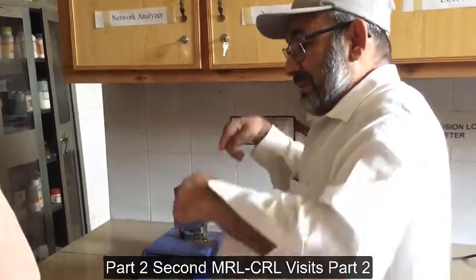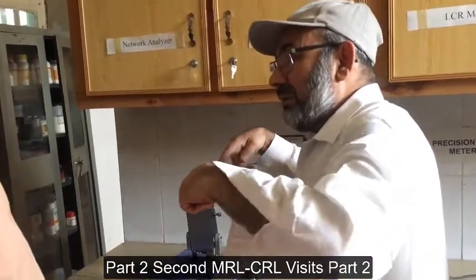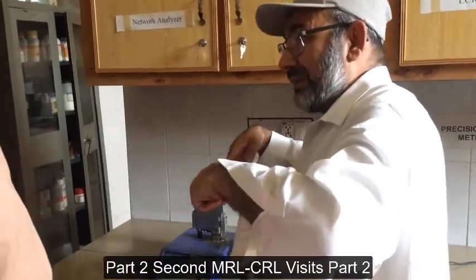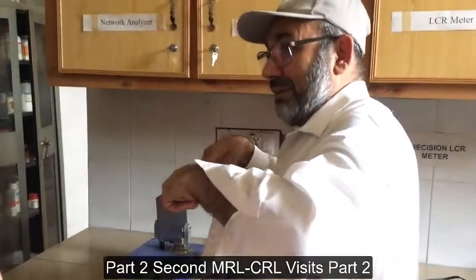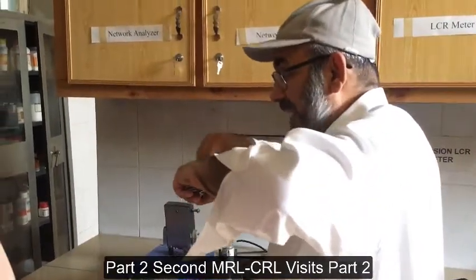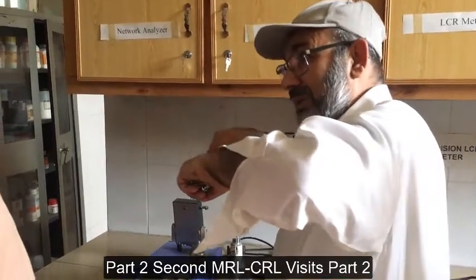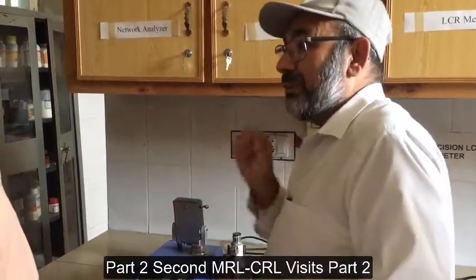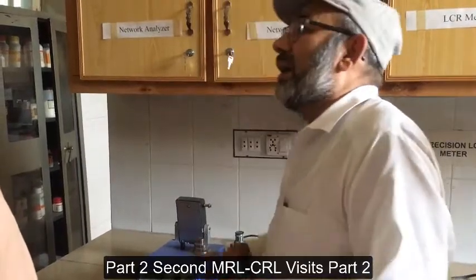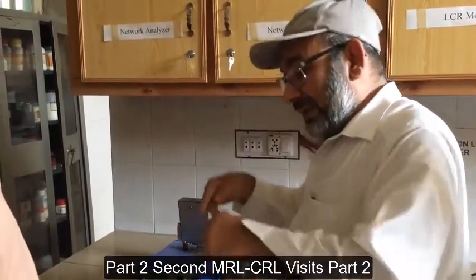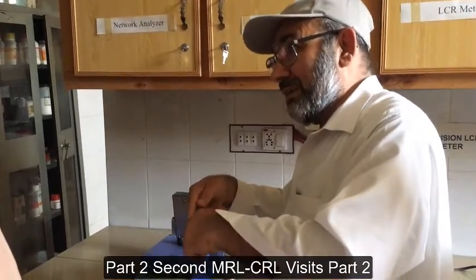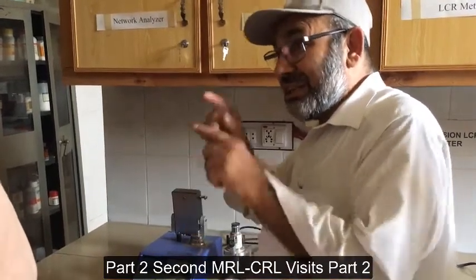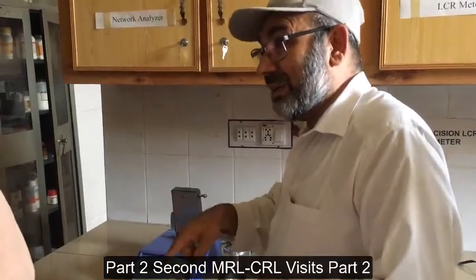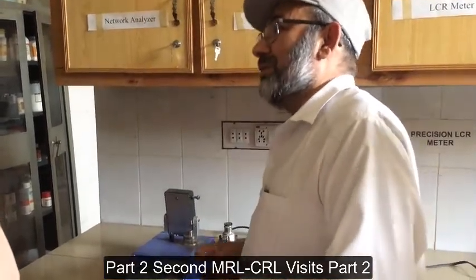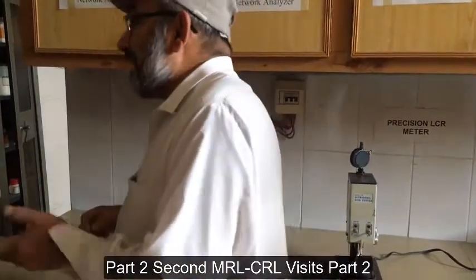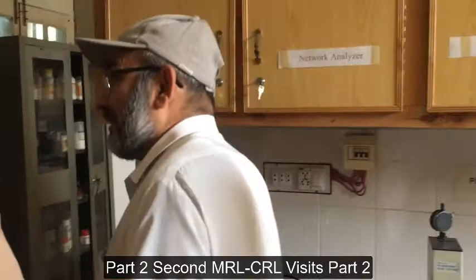Then that dimple is placed in argon beams. The ion beam thinner is a machine which is in our CRL. So argon beams are coming and scanning that dimple area of the sample, and it takes it to 20 nanometers. So the edges of the sample are around 100 micron, and the middle is thin up to 20 nanometer. When it reaches 20 nanometer, it is electron transparent, and you can use that sample in a transmission electron microscope. If it is not electron transparent, then you can't see anything in that material.